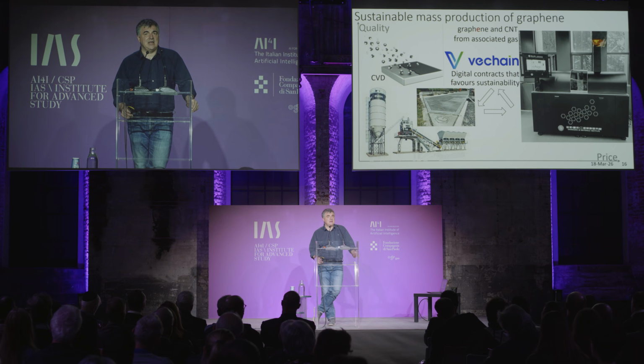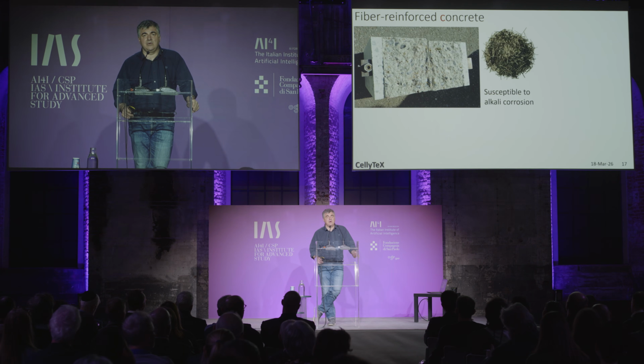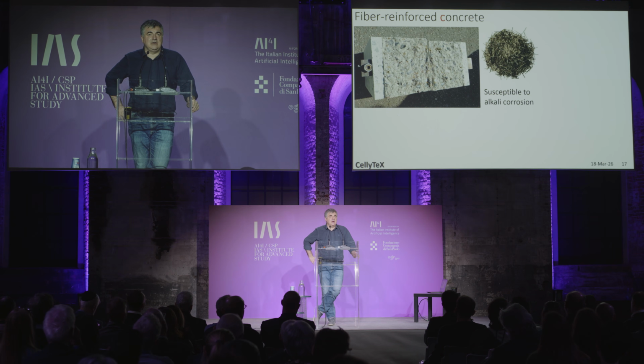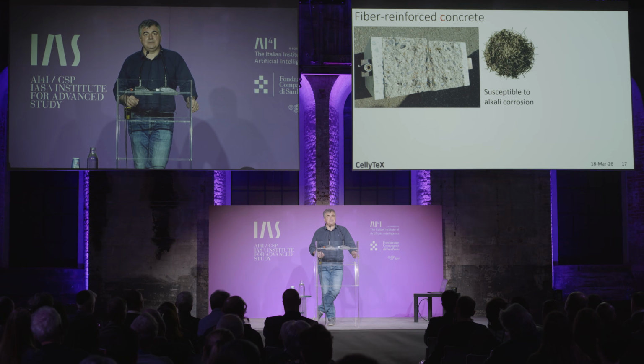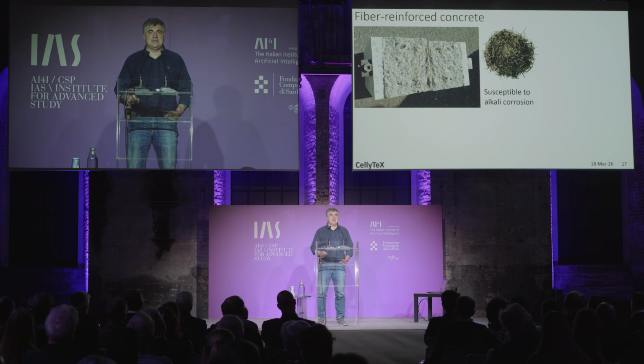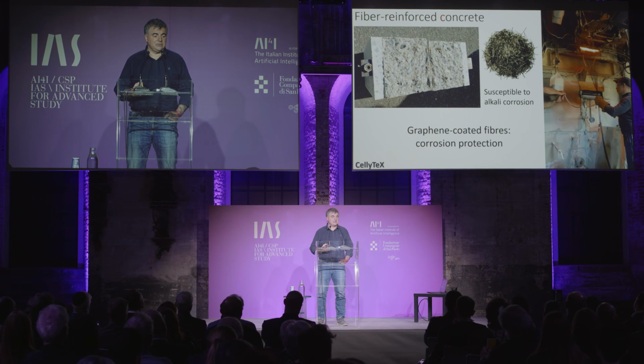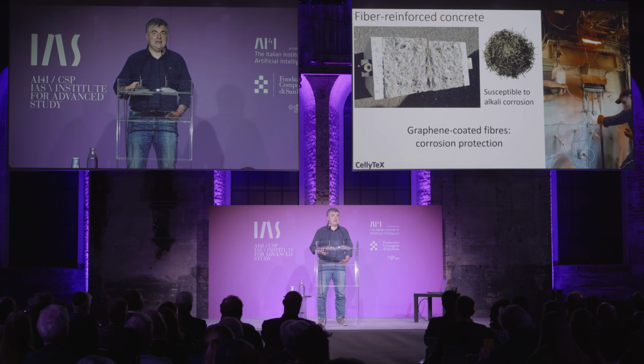Even better, it works with many other concrete structures. The new type of concrete is fibrous concrete, where you use not steel rebar but either glass fiber or mineral fiber for the reinforcement. It works really fantastically well, much easier to deposit. You don't need to put in the rebars. The problem is those fibers corrode. They don't like the high pH environment in the concrete. So what we do is coat those fibers with graphene, and then we stop the corrosion.